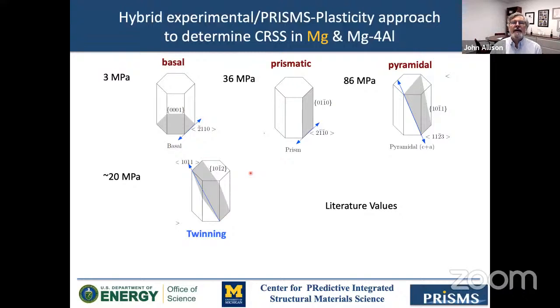So we have modeled all these experiments as well in PRISMS-Plasticity, and used this sort of hybrid of MTS cyclic stress strain, in situ twin volume fraction and PRISMS-Plasticity to determine the critical resolved shear stresses in mag and mag aluminum. So in the pure mag, what we believe are values that we would propose, we have pretty much said, yeah, the literature's right in basal, prismatic, and pyramidal, but it's very high for the twinning, and this is the growth stress, not the initiation stress. It's a little bit lower than that.